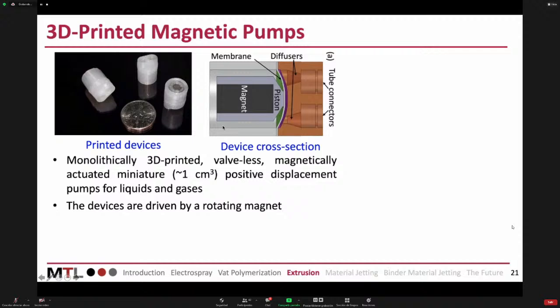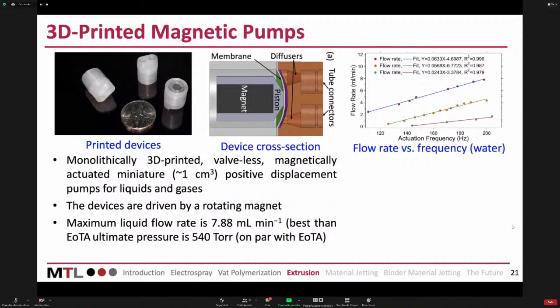This is monolithically printed, so there is no assembly. You need to keep rotating the object when you print it, but everything is put monolithically together. The magnet, the piston, the membranes, everything. And it's amazing, but it's straightforward to do with a low-cost printer, and it works very well. Look that if you use it for pumping liquids, it can pump 8 milliliters per minute, which is a lot higher than anything you can do in the clean room, because we are able to process larger pockets and operate at higher frequency. And again, this is nylon.